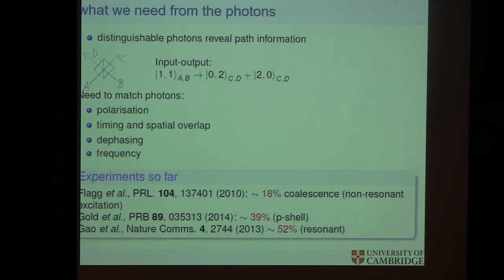You use the higher lying state to excite, and then you wait for a decay, and then you get the optical photon that comes out at the end, and you look at how reproducible these photons are. The best was 52% in the absence of any cavity enhancement. So again, I'm not showing any cavity results. They are good because you're broadening the transition itself, and that helps eat away the spectral fluctuations that you might have in the system.